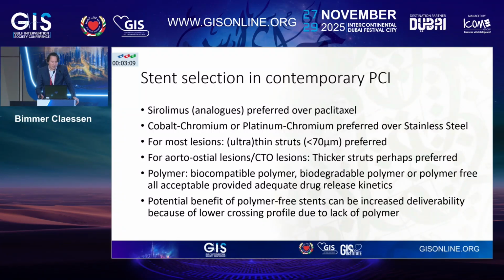So to summarize, for stent selection in contemporary PCI, sirolimus and its analogs are preferred over paclitaxel. Cobalt chromium or platinum chromium is preferred over stainless steel. But for most lesions, ultra-thin struts are preferred. However, there are certain subsets like aorto-ostial lesions, CTO lesions, maybe heavily calcified lesions, where you may prefer a little bit more radial strength and where some thicker struts may be required. The polymer does not seem to matter that much. It has to be biocompatible, biodegradable, or polymer-free. They all seem to be very acceptable, provided that they provide adequate drug release kinetics. However, a potential benefit of the polymer-free stents can be increased deliverability because of lower crossing profile due to the lack of polymer, particularly when used in a thin stent strut platform.